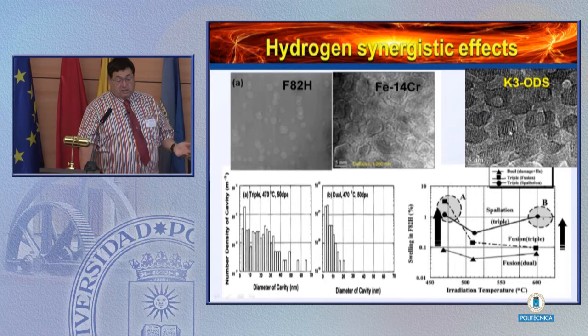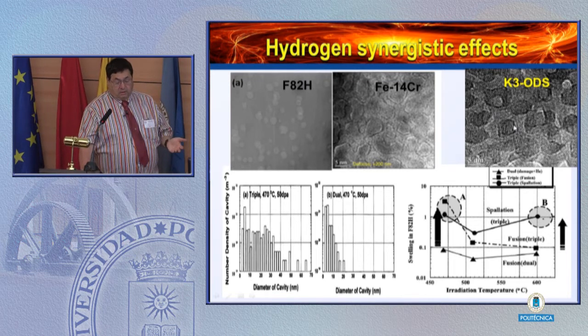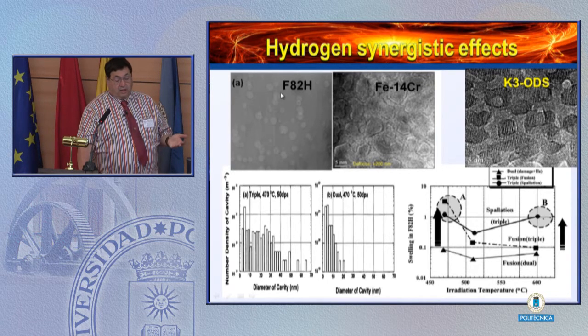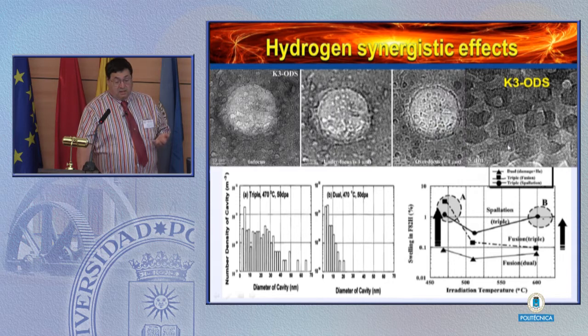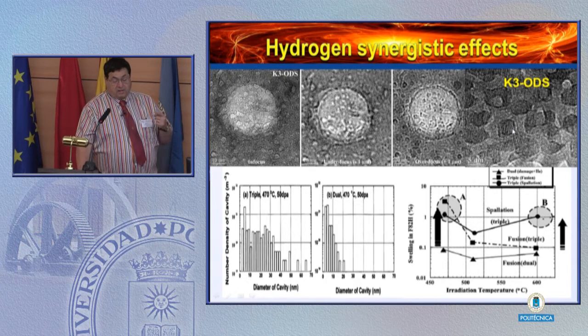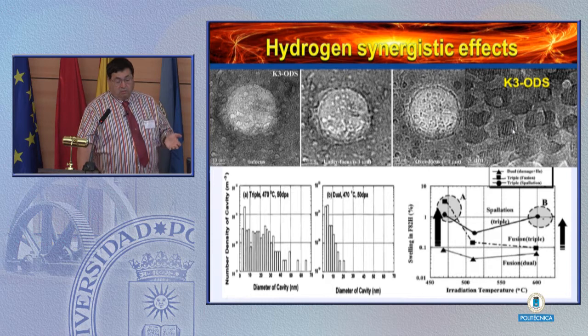And when we went to look at ODS in triple beam effect, lo and behold, we saw something like what the Japanese were seeing in the F82H and what we were seeing in iron 14 chrome, but it turned out that on analysis, this was not what was really going on. This was not just simple cavity growth, acceleration of the cavity growth, either through changing the critical radius or changing the helium uptake. We don't know what the mechanism is. This is something else. And we started to suspect that it was somehow related to another phenomenon that had been discovered by several labs, but particularly at CEA.